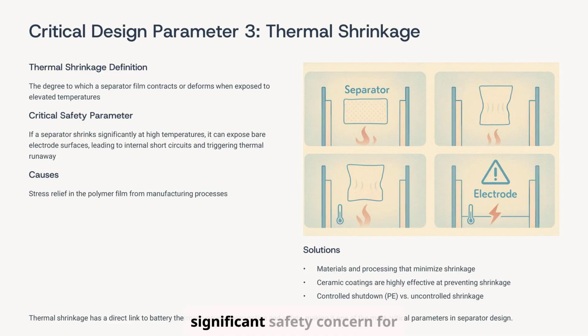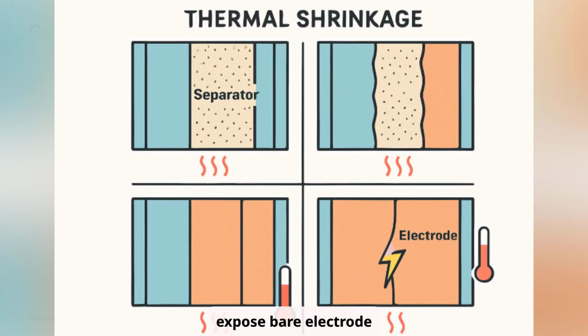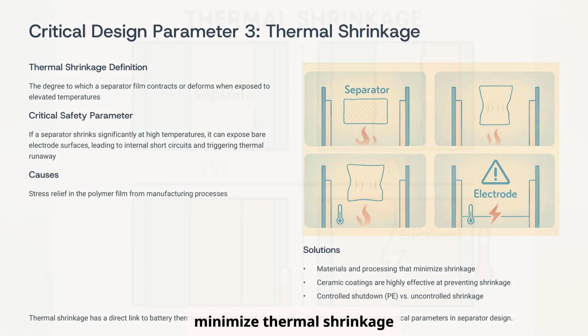Thermal shrinkage is a significant safety concern for battery separators. It describes the degree to which a separator film contracts or deforms when exposed to elevated temperatures. If a separator shrinks excessively, it can expose bare electrode surfaces, leading to internal short circuits and potentially triggering thermal runaway. Solutions to minimize thermal shrinkage include selecting materials and processing methods that inherently reduce contraction, incorporating ceramic coatings for structural stability, and designing for controlled shutdown mechanisms, such as those found in polyethylene separators, to prevent uncontrolled shrinkage.